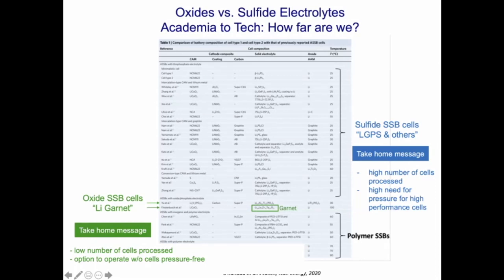When we look at this analysis, overall, oxide-based solid-state batteries are, and that's one thing to consider, less advanced in the various cell geometries and architectures that have been manufactured. So much more needs to happen, but I ascribe that to a strong tie to what is possible in terms of ceramic manufacturing, as this operates at higher temperature.